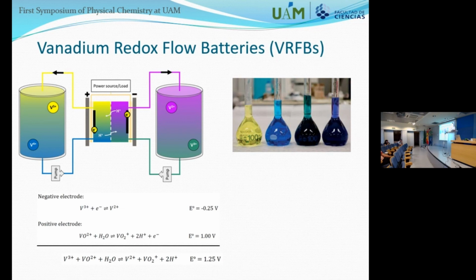This is a picture of what a vanadium redox flow battery would look like. In the negative electrode, vanadium 3+ converts to vanadium 2+. This is in the charging process. And in the positive electrode, during charging, we have the conversion of the vanadium oxide ion, in this case in the 4+ state, to the vanadium dioxide ion, in this case in the 5+ state. So here we are playing with the 4 oxidation states of the vanadium metal. And as you can see, it has very beautiful colors, so it's also a nice thing to work with these kinds of batteries.